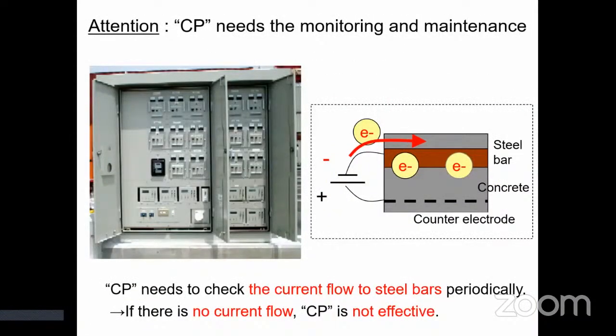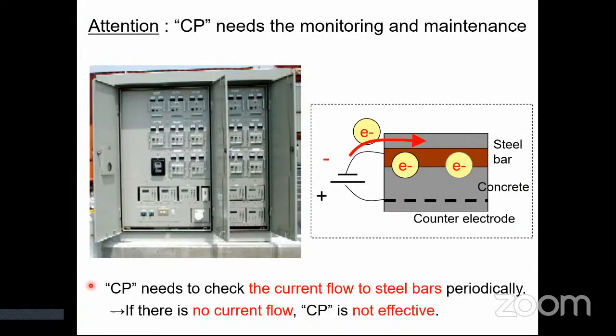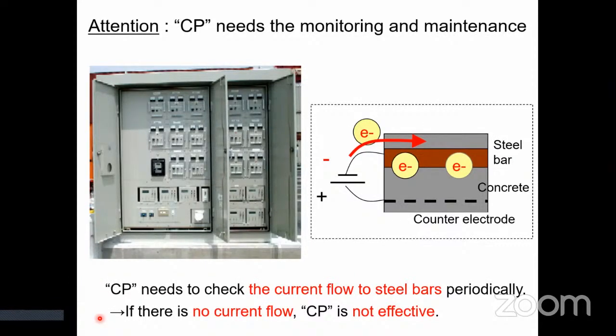In the application of cathodic protection, we need monitoring and maintenance. We need to check the electric current flow to the steel bar periodically. Because if there is no current flow, cathodic protection is not effective.